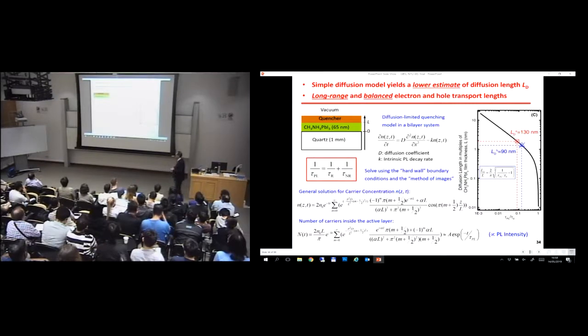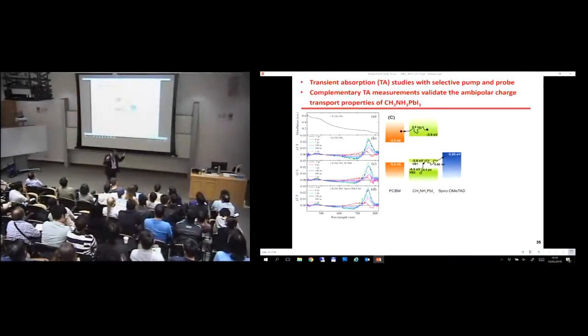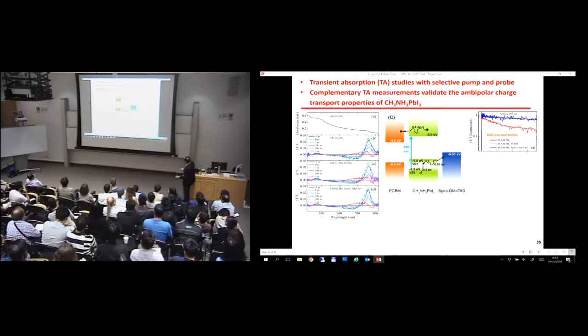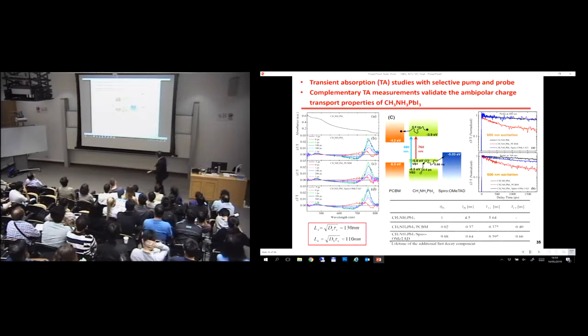solution-processed material. We were a bit skeptical, thinking, hey, this is a PL experiment; we may just be looking at the emissive species. So let's try another approach: pump-probe spectroscopy. Pump-probe, or transient absorption spectroscopy, does not just monitor the emissive species, it also monitors the non-radiative species as well. So we do a selective pump and a selective probe of the levels, measure the lifetimes from the recombination, and indeed it validates the PL experiments: the diffusion lengths are indeed long, of the order of hundreds of nanometers.